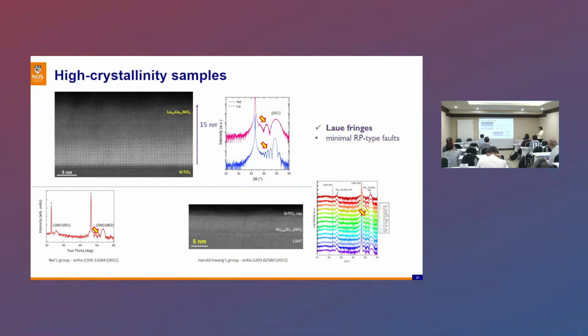But just to point out Carsten's point just now, claiming that this is a high quality sample is not really true, because in the previous sample it's also within 5 nanometers you always have a very nice infinite layer. While this sample is actually limited only to 5 nanometers. So it's not a thick sample. So that cannot really be said for high quality samples in the case that you put this on the LSAT substrate.